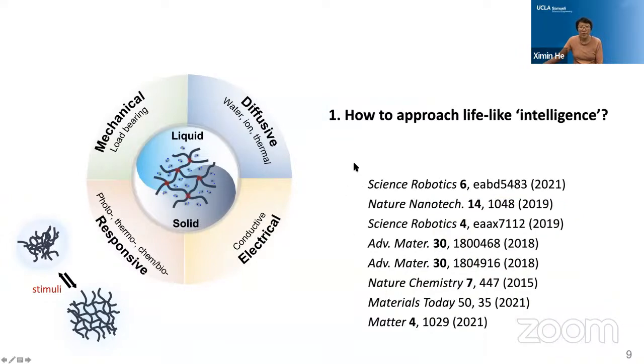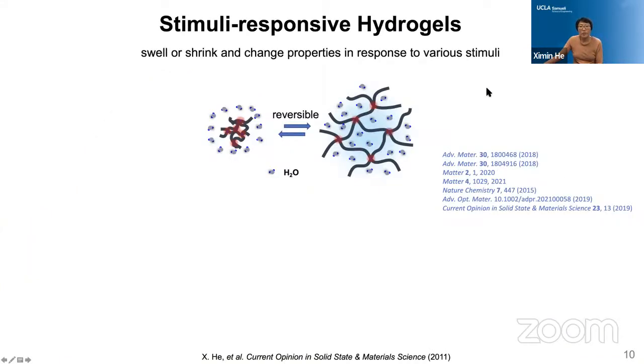All right, so first I will show you a couple of stories of how we can utilize this stimuli responsiveness to approach so-called lifelike intelligence. All right, so just briefly about the stimuli responsive mechanisms. The hydrogel networks can undergo swelling and shrinking by absorbing the water molecule inside of the polymer network or squeezing the water molecule out of the polymer network, which will undergo this volumetric change. And associated with this, the physical or other mechanical diffusive properties may change as well.